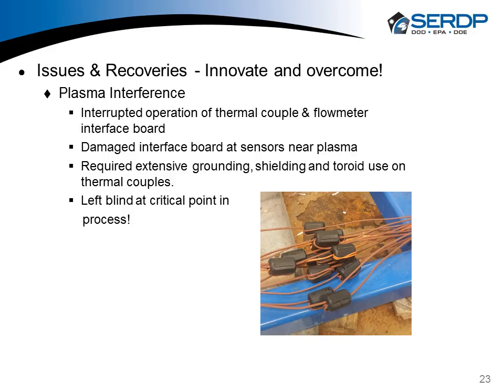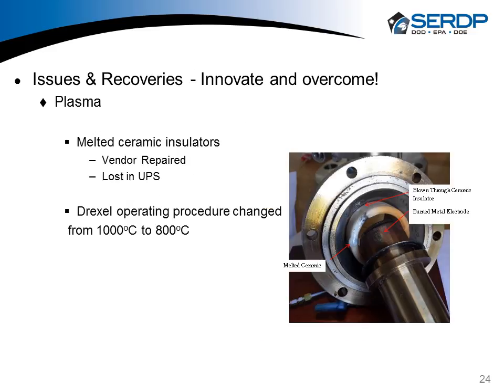Before we replaced it, we used the remaining channels to figure out what we had to do to protect everything, and we wound up putting toroids all over, putting shielding and grounding, and what really was unfortunate is that it kept us blind at the critical point downstream of the plasma. There was just too much energy going on there, and we couldn't get a real good reading on temperature coming out of the plasma, so that kind of created some heartache. The plasma had its own set of issues too.